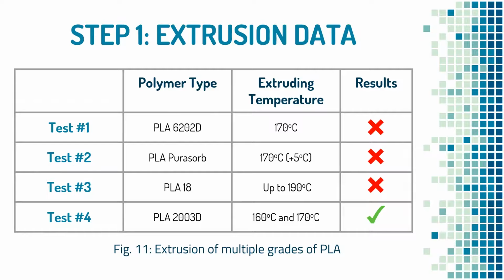So we tested 4 different grades of PLA. The first 3 grades were unsuccessful. They were too brittle to be spooled, like uncooked spaghetti. The last grade, 2003D, was successful. It was elastic and strong enough to be spooled, and served as the grade of PLA that we used for the remainder of our experiments.